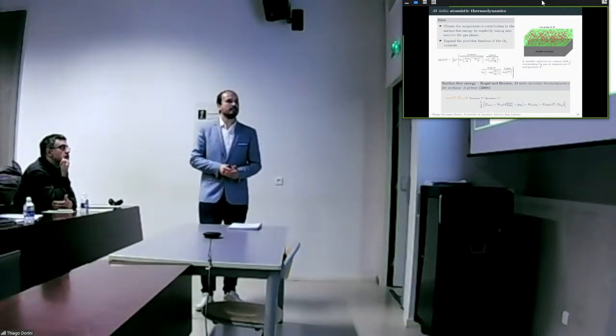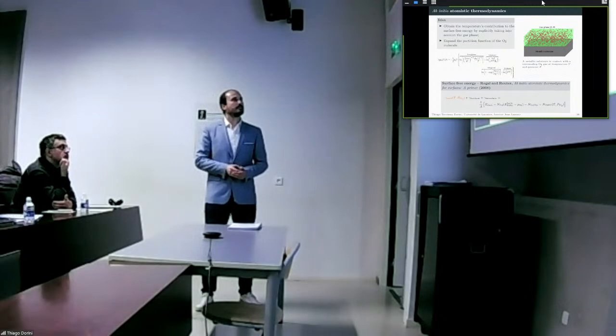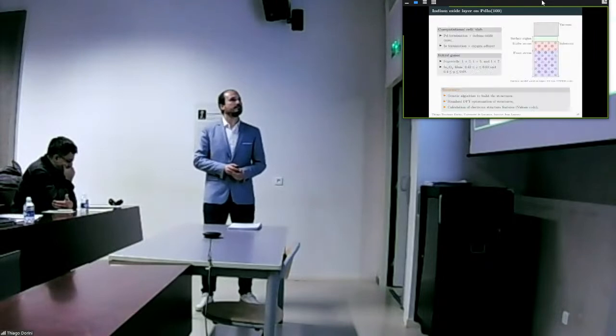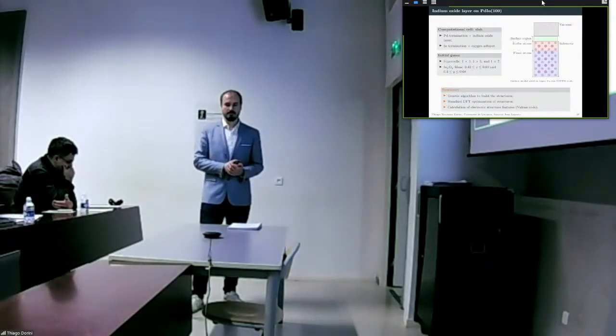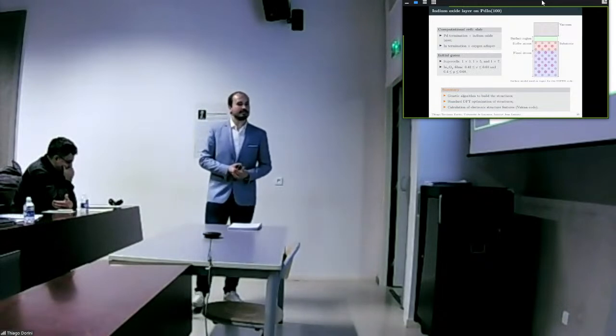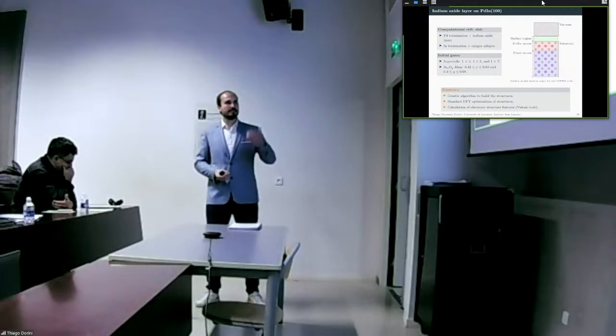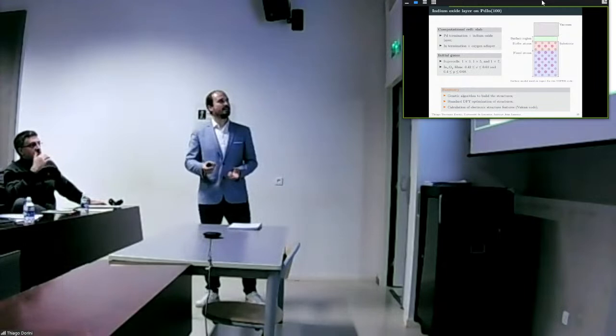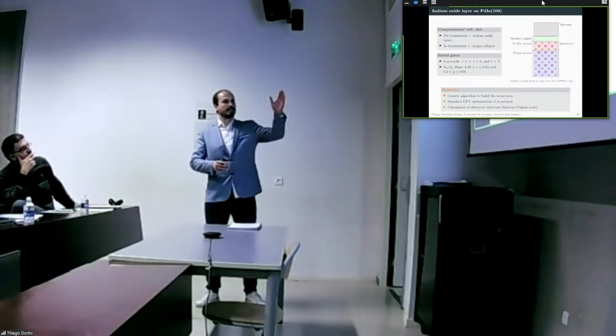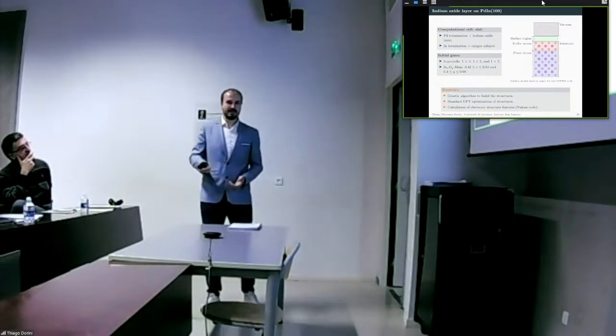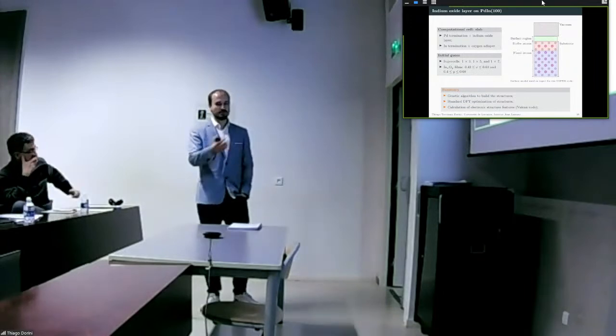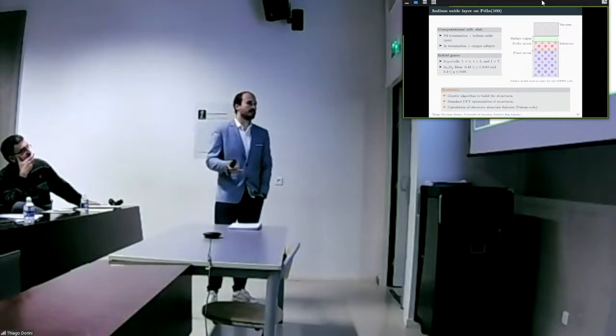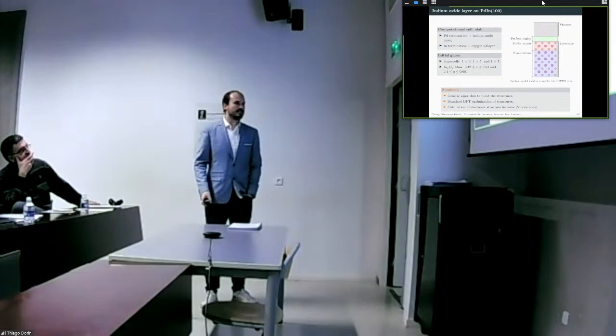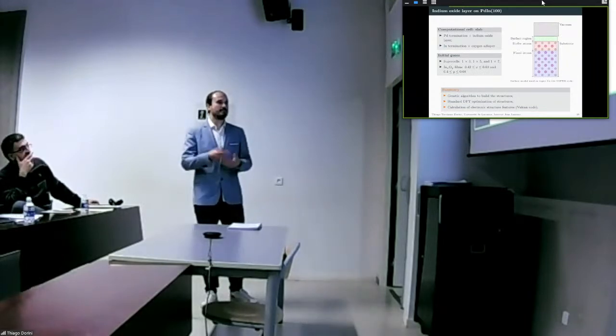Okay, and what about the choices you made at the beginning? Because you have the 1x7, the 1x5, the 1x3. What about choosing, for instance, 2x2 or something like that, in order to be able to expand a bit in all the 2D dimensions? Yeah, this is a great question. We had experimental evidence that the structure might be a 1x7, so we started from this, and we selected the 1x3 and 1x5. But in fact, after this, we also began to use a 2x2 or even a 2x3, but the calculations were not finished. That's why I only show this. But it's really a great idea to expand this and try to see some other patterns on different substrates.